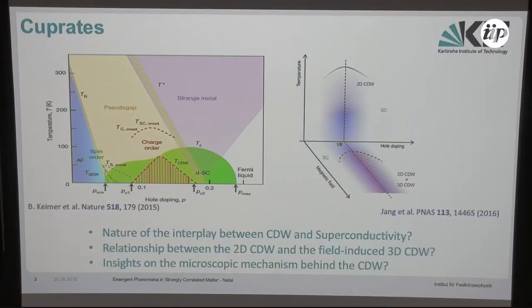But there's a second phase diagram, which is what happens when you put a magnetic field. It was recently found, so we heard from Baptiste about the Fermi surface reconstructions, about the quantum oscillations, and this kind of thing. I'm not going to talk too much about that, but from the X-ray perspective, or from the structural point of view, it was found that above a certain magnetic field, around something like 15 Tesla, instead of this 2D charge order that we see in the absence of magnetic field, there's a new 3D charge order that sets in, a really long-range charge order, when superconductivity is suppressed. And the relationship between the 2D and the 3D charge order is also something we would like to understand better, and maybe through this understanding get some insight regarding the microscopic mechanism yielding the formation of the charge density waves.